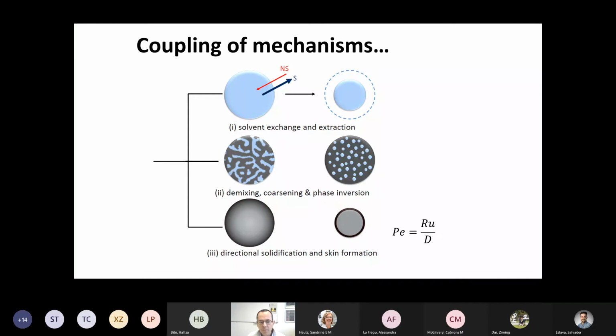So how can we try to break these down into bits so that we can make sense of things? So clearly there is a shrinkage that takes place. So the solvent that is within the drying droplet is being removed, but also we've seen in the case of the levitation, but also in the case here, we might have also non-solvent coming into the droplet. So there's a solvent exchange, a diffusive process at the interface. You might have some kind of demixing, which can be spinodal, for example, or perhaps through some kind of nucleation and growth process, which is the one you saw just on the last image. And then this process is clearly directional, so it's emanating from the interface into the bulk. And so you expect there to be a gradient.